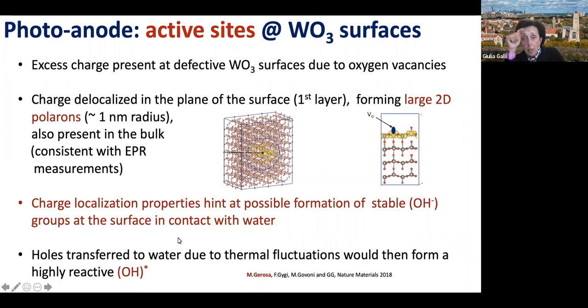So because you have charge at the surface, this hints at the possible formation of a stable OH minus. When the holes that you get from absorbing light are actually transferred to the water due to thermal fluctuation, then you have most likely a reactive OH group that is going to be involved in the splitting reaction. So this is a nice result, but note that all these results are based on calculations where the real dynamics of the holes and the electrons has not been dealt with yet. So we have hints of what may be happening, but it has not been dealt with yet.